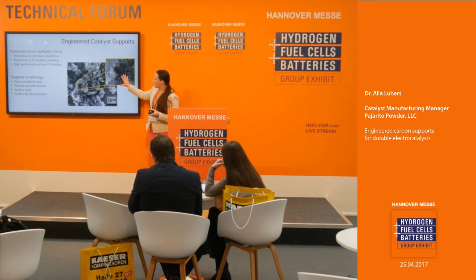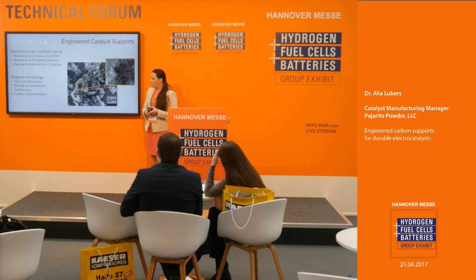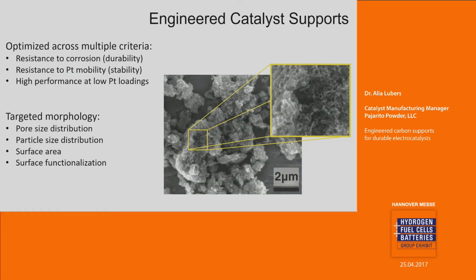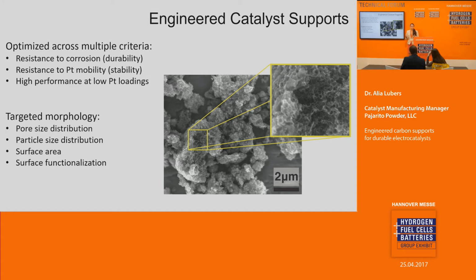So, in general, most of our materials look like this, mainly made of carbon. The point of our engineered catalyst support is to mainly address carbon corrosion within the cell. So this will improve durability and increase device lifetimes. We also want to improve the ability to make a catalyst system, so deposit platinum onto our engineered catalyst support, and to make carbon that makes it easier to deposit that platinum. How we achieve this is by influencing the characteristics of the carbon itself. That can include primary particle size, pore size, surface area, and also if you have any functional groups on the carbon itself.